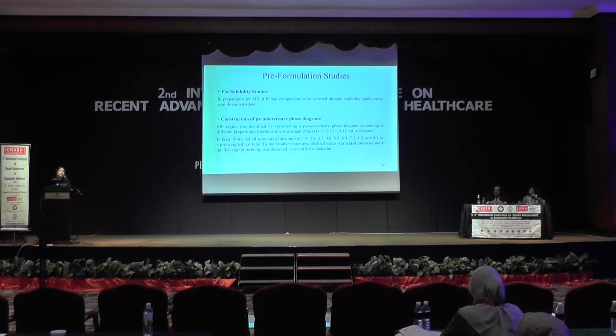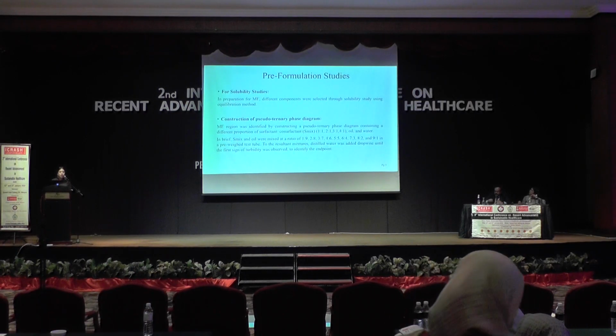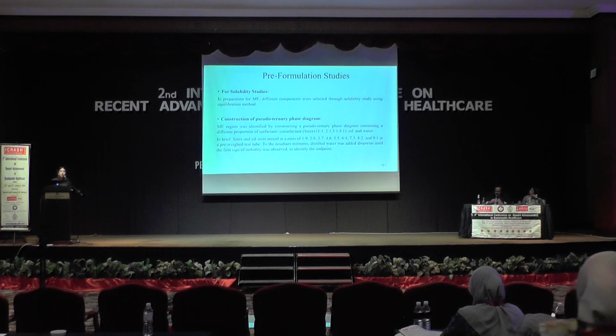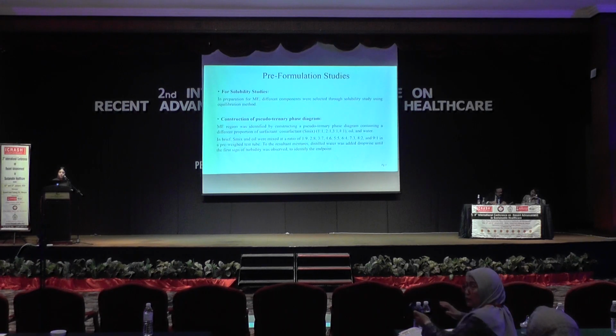First I did the pre-formulation studies. For this I checked the compatibility of diacerein with the other constituents, whether it is soluble in the other constituents like the castor oil or not. And then I did the pseudo-ternary phase diagram. I chose 4 types of ratios of the surfactant and co-surfactant, and then 9 batches of the formulations were made by changing the ratio of castor oil. And then distilled water was added dropwise until turbidity was observed at the end point.